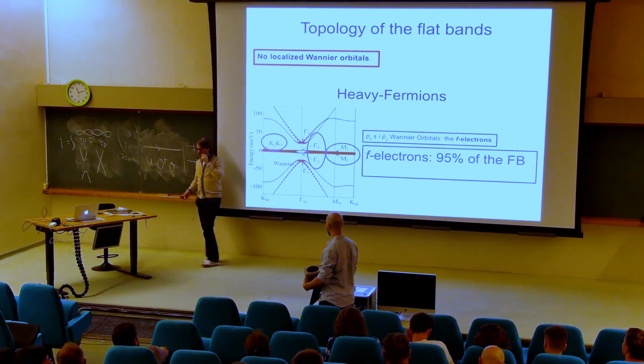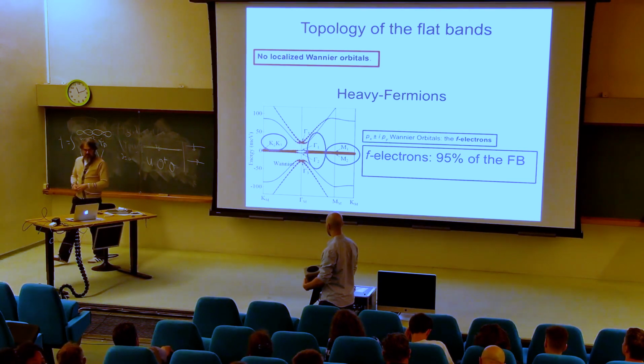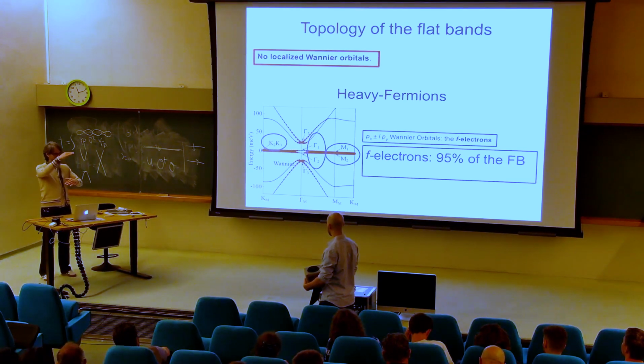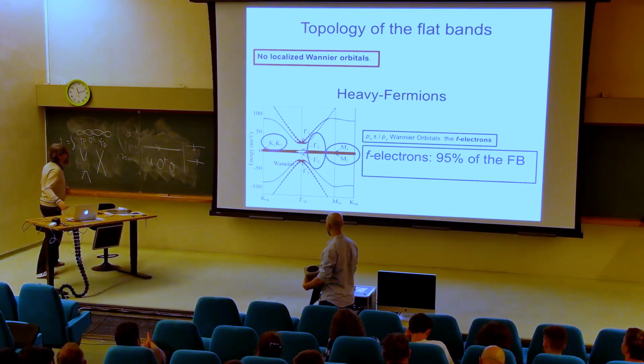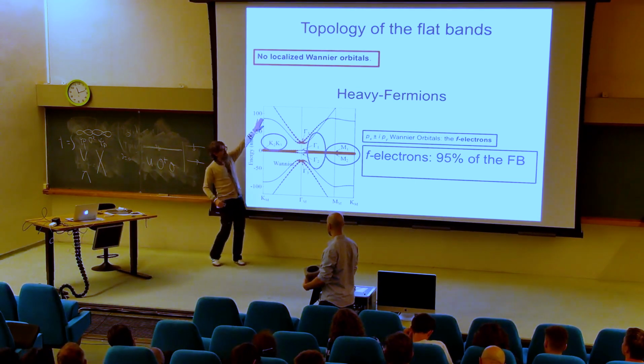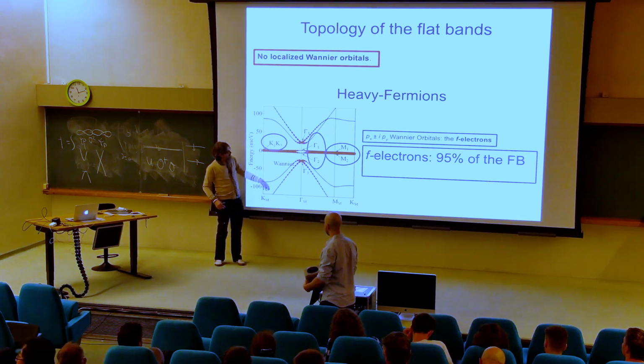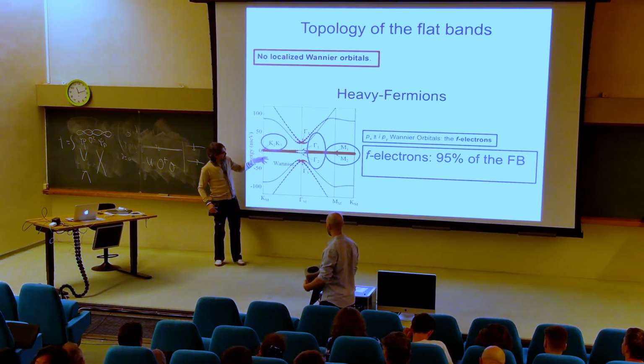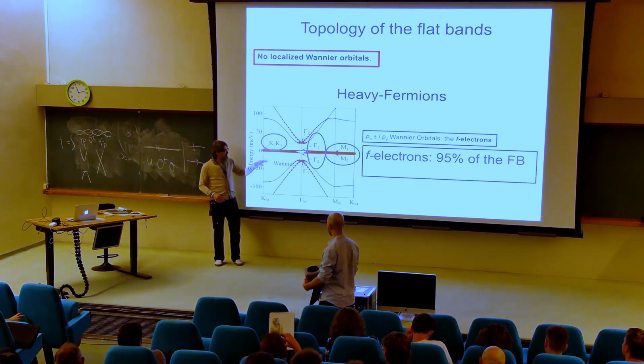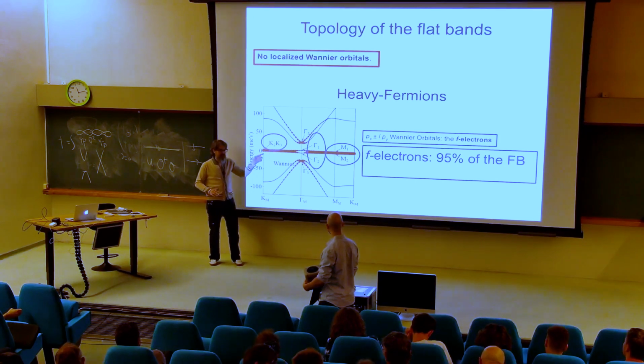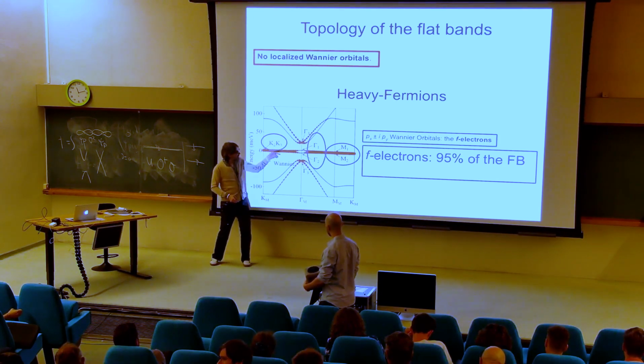So there is an algorithmic way of doing it, which is you look within the Hubbard U and ask, what are all the bands? Within the Hubbard U, I don't have this band. These ones cannot matter here because, first of all, they're outside of the Hubbard U range. Also, the further you are, there's no Berry phase, because the band gap gets large. So I know if I have a large band gap at some K point, I can't have any Berry phase there for the flat band. So that's why these are flat here, right? So that's why they're heavy here. Heavy means no Berry phase.